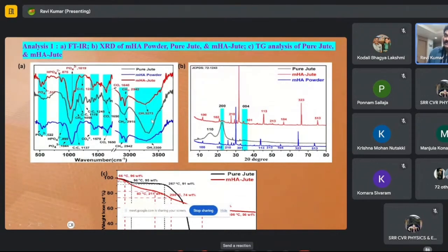I already showed this in the chemical structure. The chemical structure already has many OH functional groups on the hemicellulose, and that group is shown here. So the MHA jute, the MHA powder, and the pure jute can be distinguished easily, and the phosphate and HPO4 groups appear very clearly on the surface. It means the surface is strongly decorated by phosphate groups, so the deposition of MHA is strongly evident on the surface.